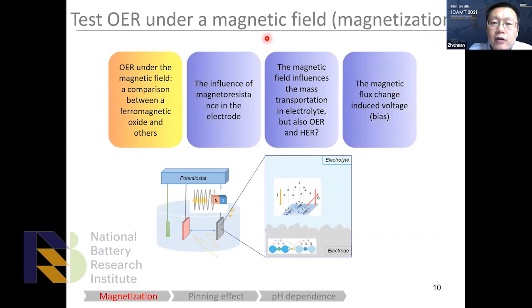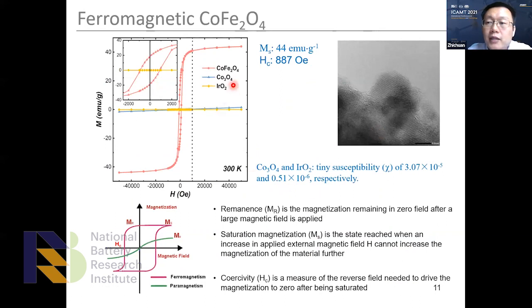However, we have to be very careful, because applying a magnetic field on the electrochemical system will cause many other changes. If we observe a difference, say an increment in a magnetic field, the increment might come from the resistance change of the electrode, or promoted mass transport in the electrolyte near the electrode surface, or, according to Faraday's law, a generated bias applied on the working electrode. So we must be very careful to exclude these things and then draw a conclusion on whether that is true or not.